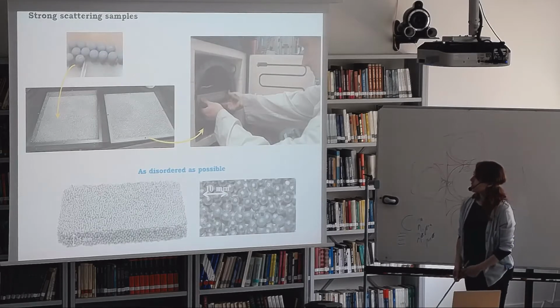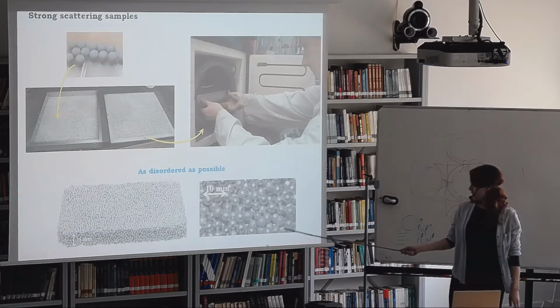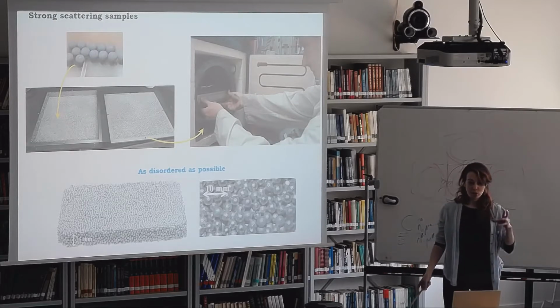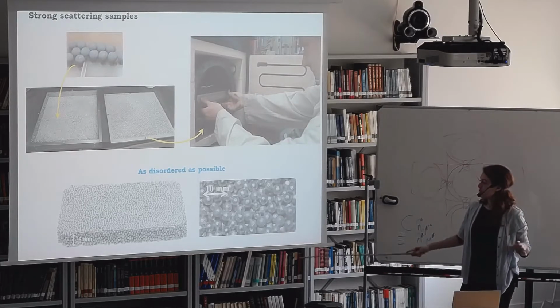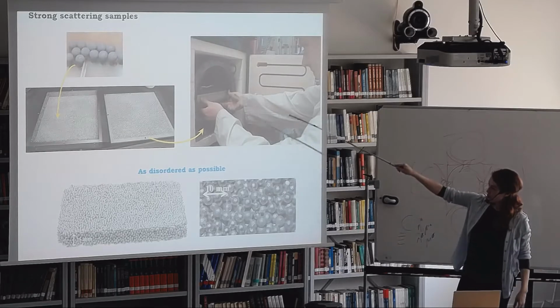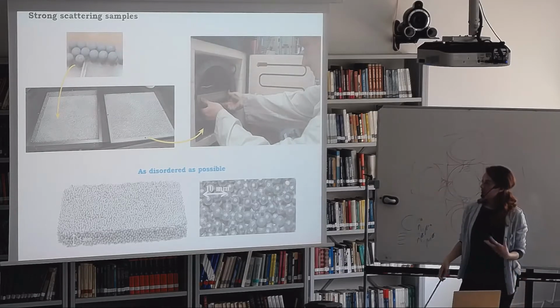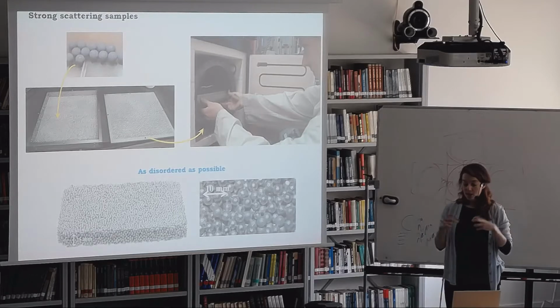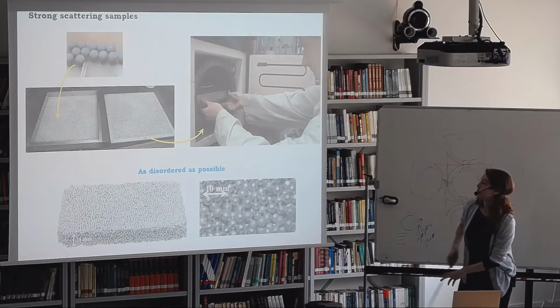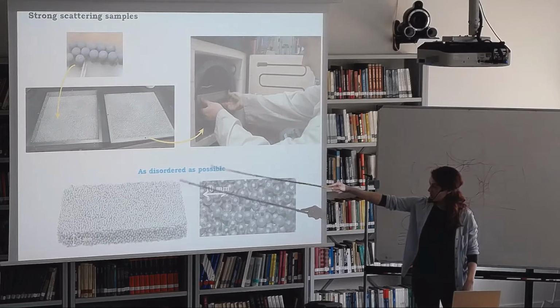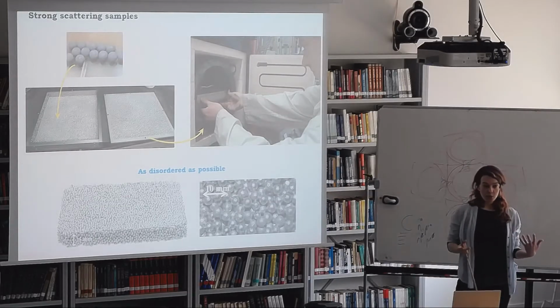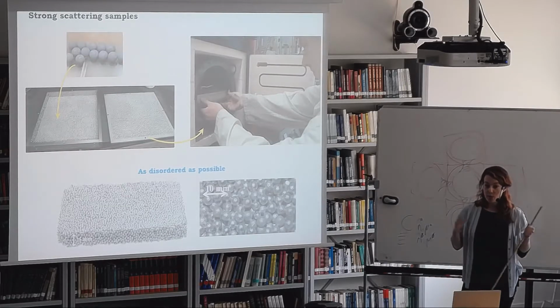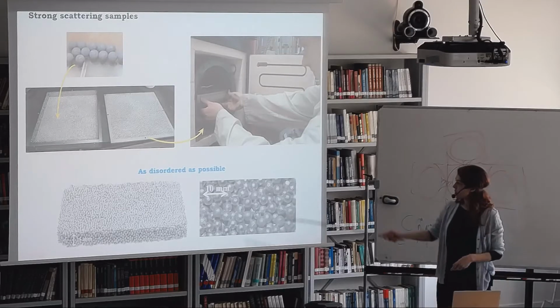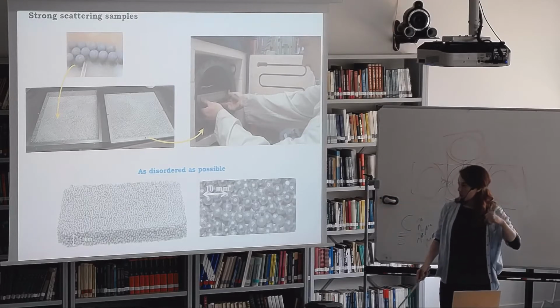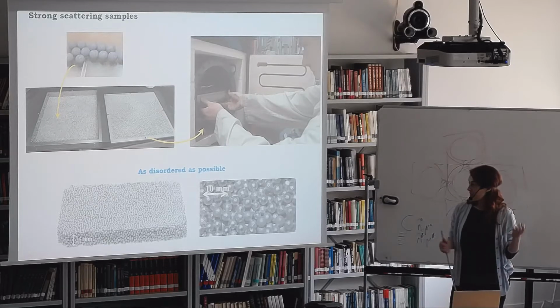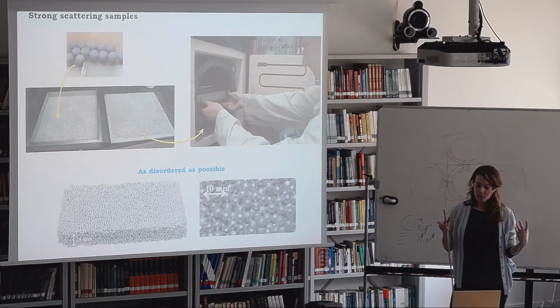OK, so here are the samples that we make. They're these sintered aluminum bead samples like we saw before with the cubes. But here we're going to make big slabs of them. So we start with individual beads, and we coat them in a material that lets them sinter together at high temperatures. So we put them in a big metal mold, such as we see here. And so we want the beads to be as disordered as possible so that they can correspond to the random walker model. So that's why this mold has essentially a bunch of dents that are randomly placed and with random depths so that the beads don't sort of self-order into a crystal.